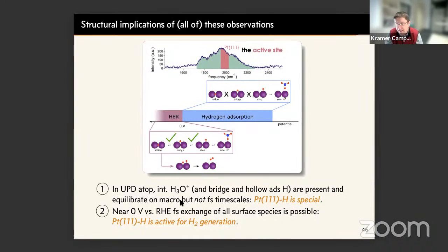So this is just an attempt to explain this, and I apologize, everyone's been here a long time, in a kind of cartoon form. What we think happens within the UPD, within the hydrogen adsorption region, is that there can be multiple types of adsorbed hydrogen, and that at least one, this platinum 1-1-1 facet, appears not to exchange with other kinds of species. We can discuss whether it should exchange here or not. Whatever the details of this surface stabilized state, it is apparent that as one approaches 0 volts on ultrafast timescales, this stabilization is gone. On ultrafast timescales now, this particular type of surface adsorbed hydrogen can exchange with all other surface adsorbed features. So what I want to suggest now is that this change in mobility is the causative factor of the onset of H2 generation.